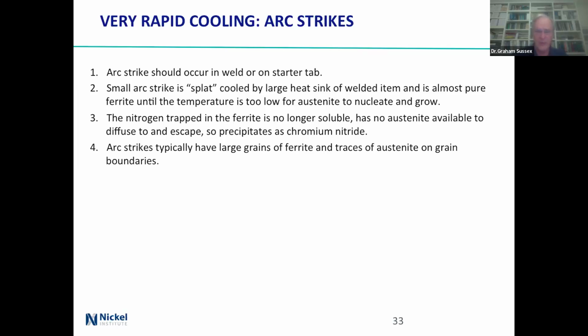Mind you, I've got that the wrong way around. Yeah, okay. There's no austenite to actually take up the nitrogen. And so the nitrogen precipitates out of the ferrite, combines with the chromium, and you wind up with chromium nitride. Chromium nitride means the chromium is tied up with the nitrogen, so you've got less corrosion resistance. And so you wind up with a problem.